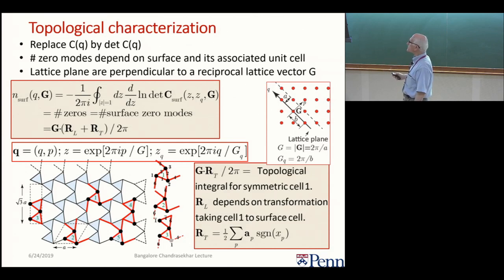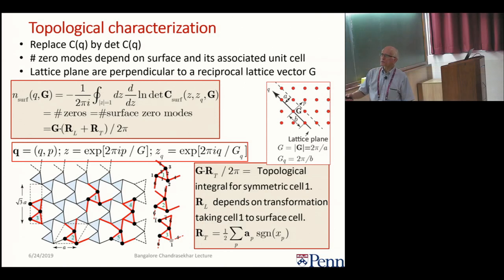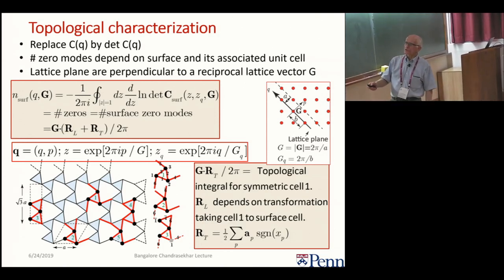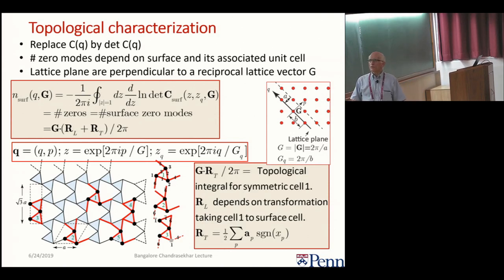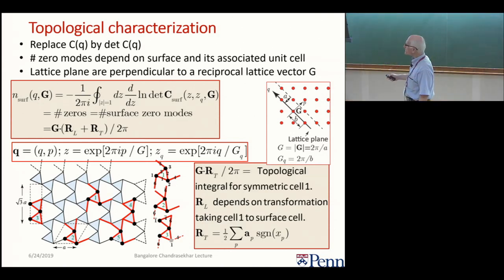So you can express this C, and I put a surface here, meaning it has to do with the surface, and I'll tell you more about that in a minute, where Z is e to the iQ, and Z is e to the iP over G going in. The question is, can we find a solution where this actually decays instead of being imaginary? And the answer is yes, and this gives you the count. But you have to choose a unit cell which is compatible with the surface.